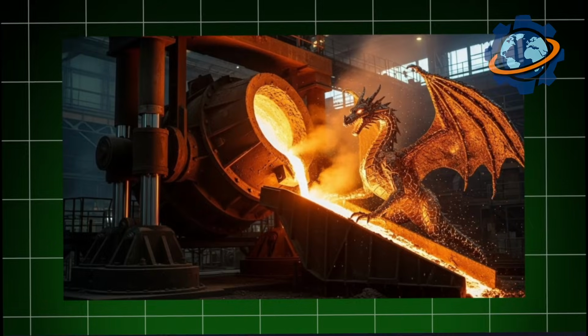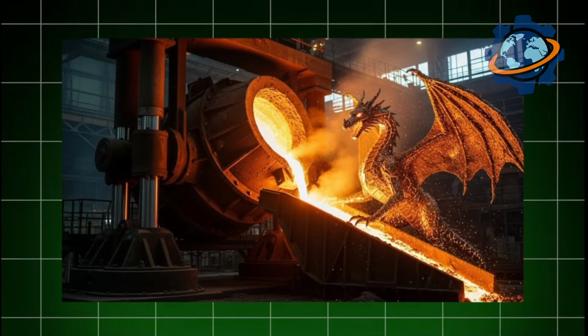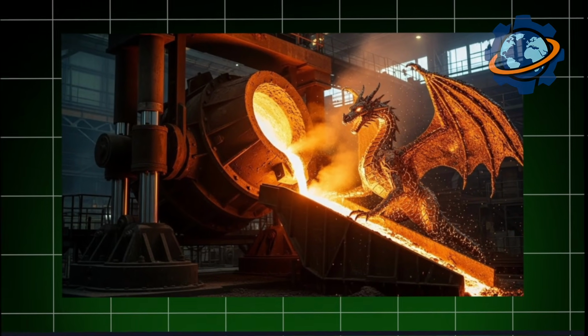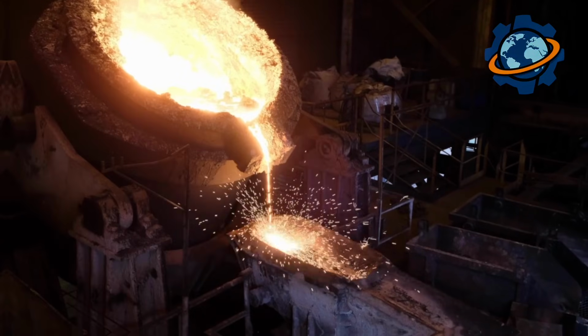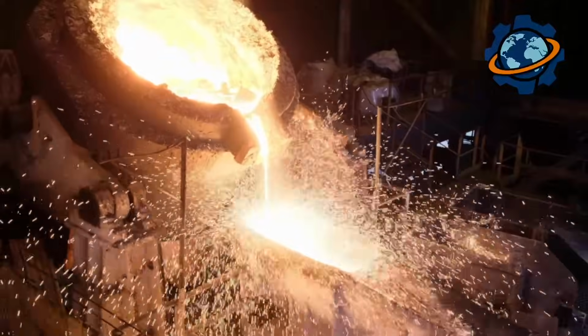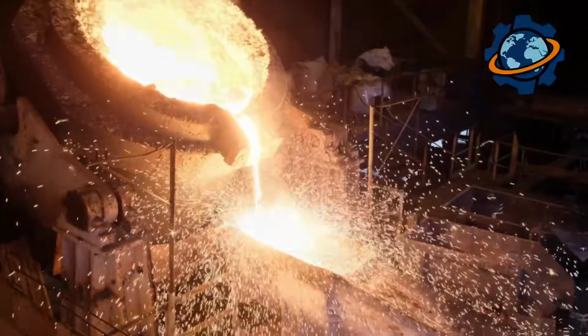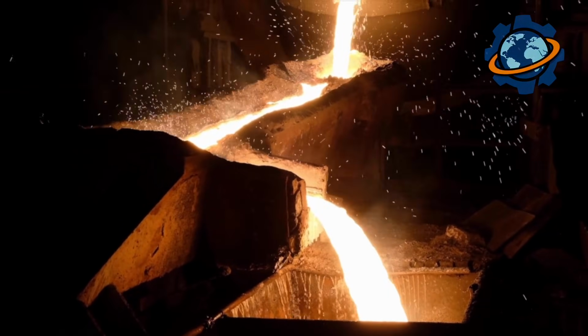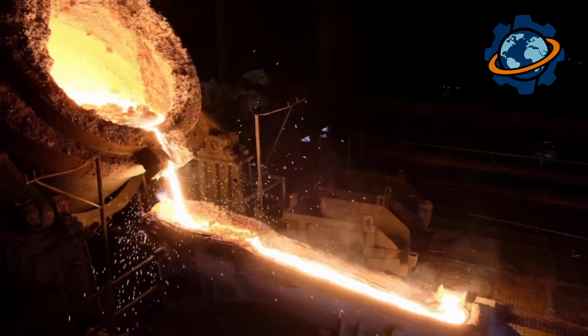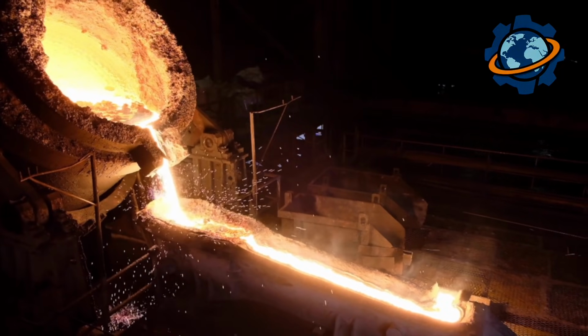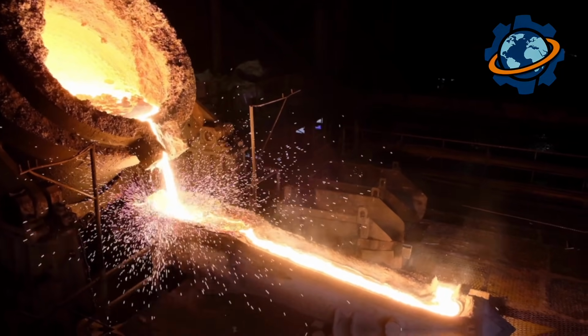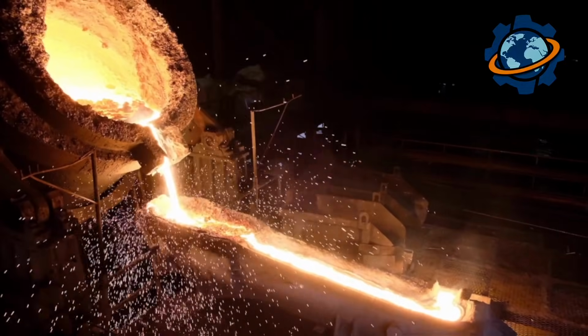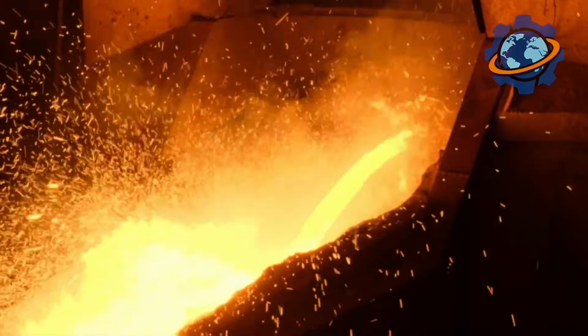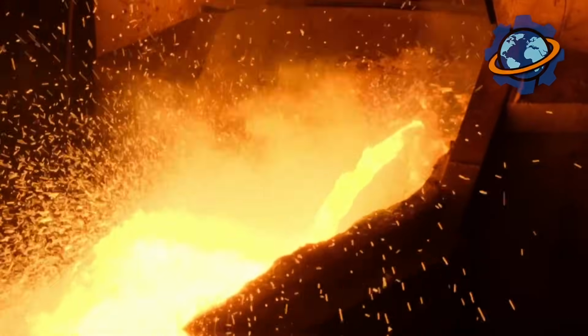Tapping releases the dragon. The furnace tilts hydraulically, massive vessel rotating on trunnions. Molten steel pours through tap hole into waiting ladle, refractory lined bucket containing 40 tons of liquid metal. The pour takes 6 minutes, continuous stream of glowing steel creating updrafts so powerful, they lift dust and debris into the air. The temperature, 3,050 degrees, radiates heat felt 200 feet away.